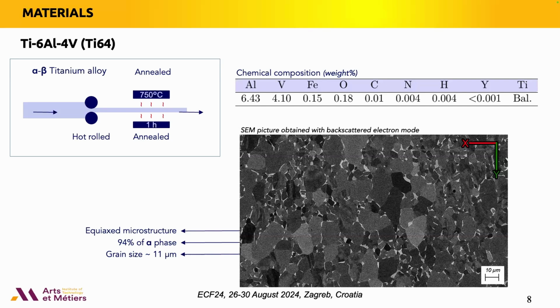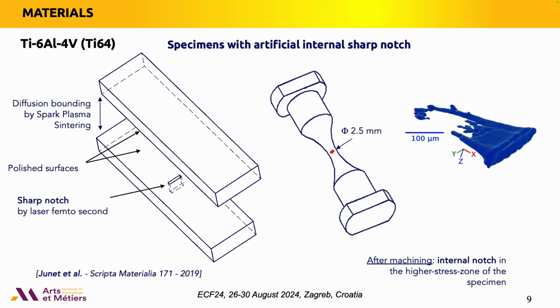So in such an alloy, since it is produced by hot rolling, we are not able to introduce an artificial defect easily by the manufacturing. So we decided to introduce an artificial defect with a special procedure. It has been prepared and defined by Arnaud Junet. It is published in this paper in Scripta Materialia. So the process is the following. You cut small pieces in a flat titanium sheet, and we produce at the surface of one sheet a very small sharp notch by a femtosecond laser.